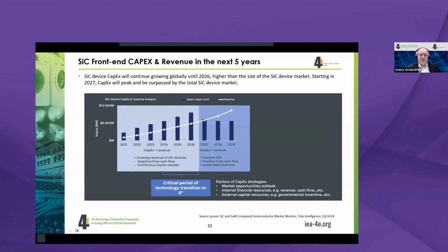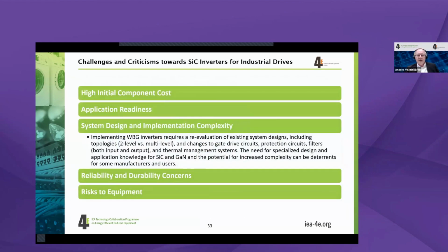They are under a heavy pressure because their capex is actually much bigger than the revenue at the moment with all the transition they're making, and it's expected that the capex will be smaller than the revenue only starting 2027 or later. This line could be even going. So at the moment, the industry is facing an issue while they're building up the capacity. And if you're building up capacity and you don't have the amount of customers in one sector, you try to get into the other sector, and that might be an opportunity for industrial inverters.